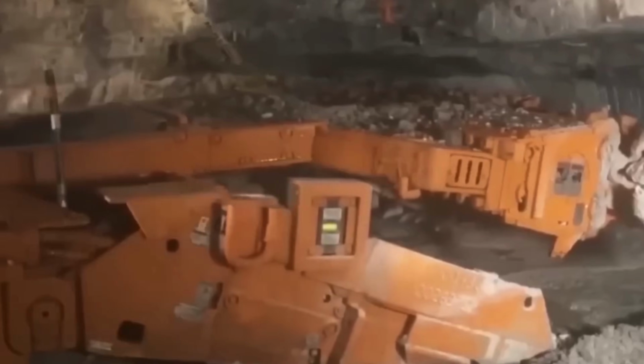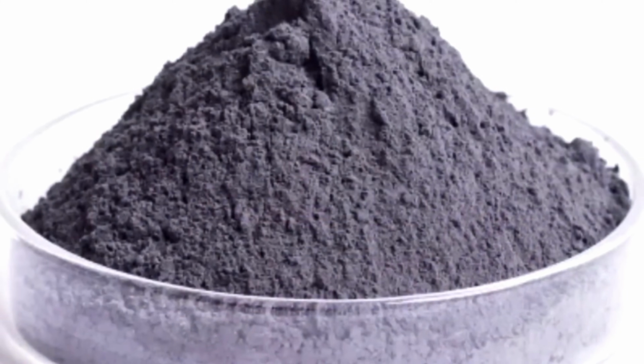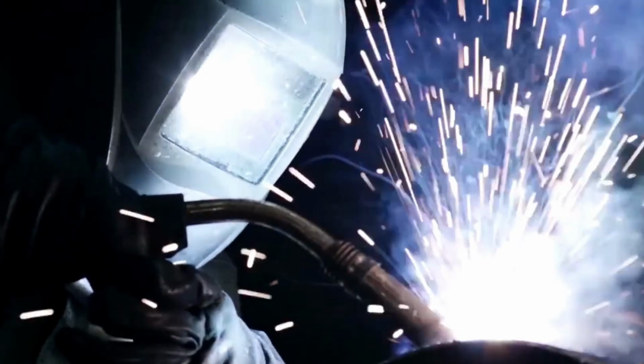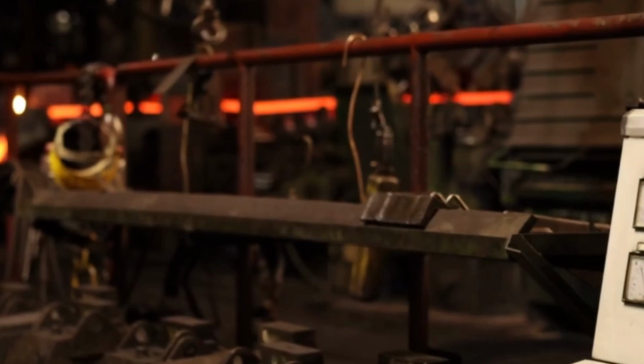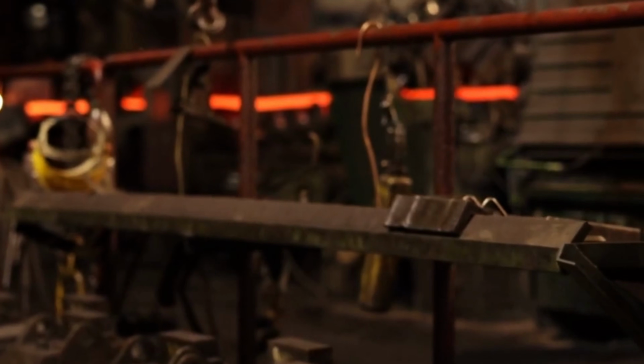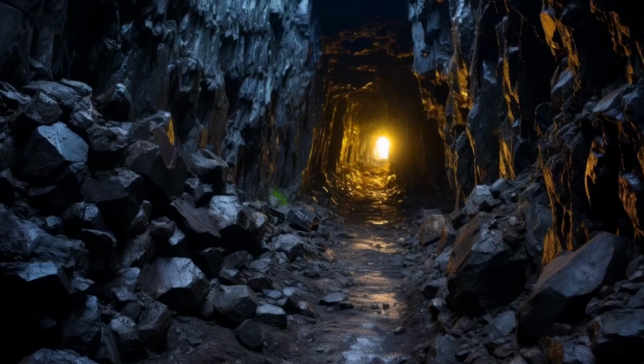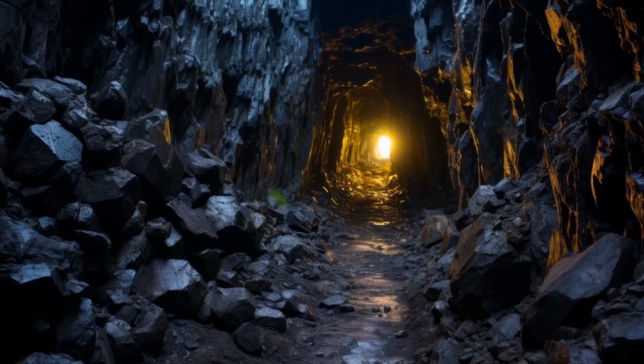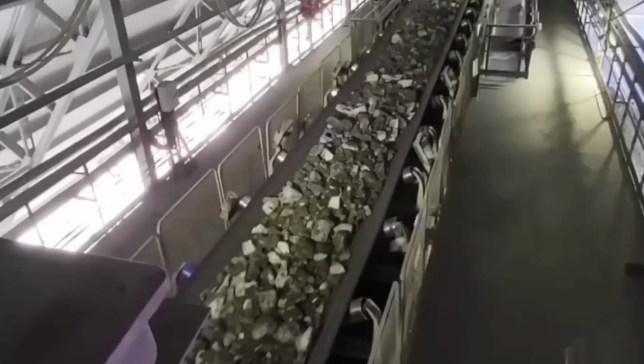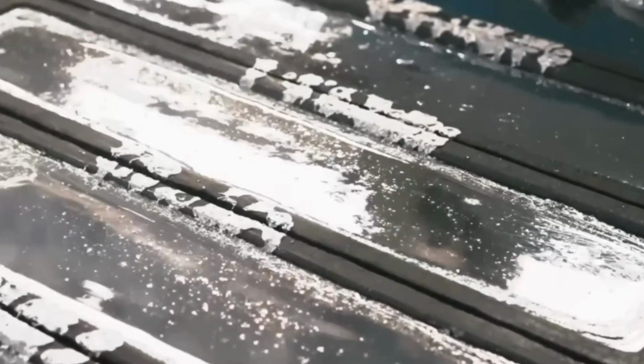From dense ore extracted from the ground to purified chemical crystals, from hydrogen reduction to powdered tungsten metal, from carbide mixing and sintering to diamond grinding and tool finishing, tungsten's journey is one of the most advanced material production processes in industry. And that is exactly how tungsten is mined, concentrated, chemically refined, reduced into powder, transformed into carbide, pressed, sintered, and finished, turning heavy stone into one of the toughest and most heat-resistant metals on Earth.